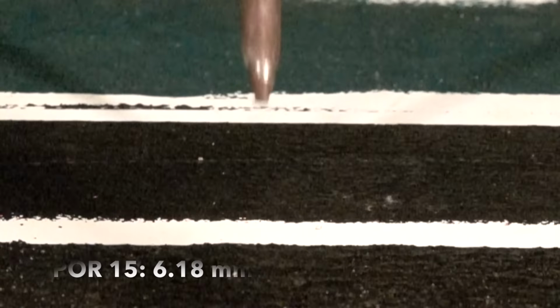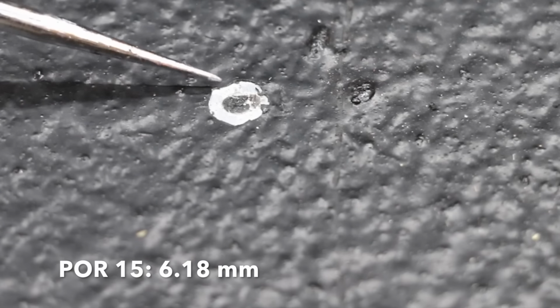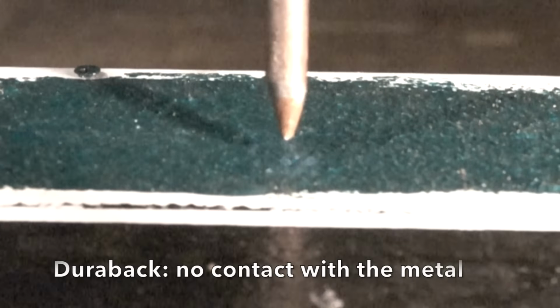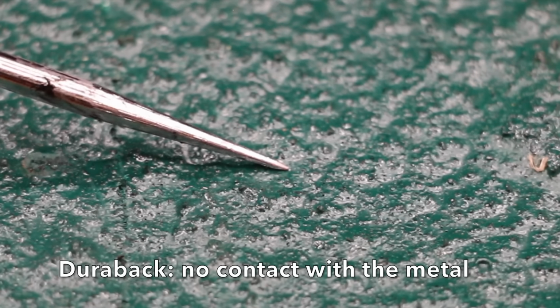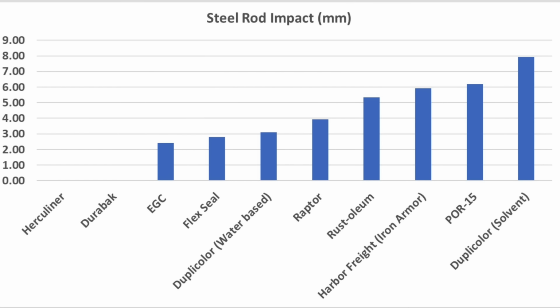The size of the damaged area with POR-15 was 6.18 millimeters. The steel rod left a very small mark but did not appear to penetrate the Durabak bedliner. So Herculiner and Durabak tied for first, EGC third, Flex Seal fourth, and the water-based Dupli-Color fifth.